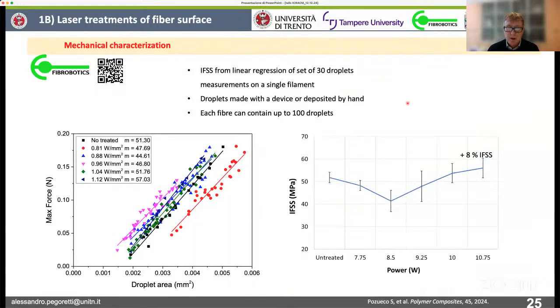The advantage of this technique is that a lot of points can be collected, so we can change the droplet area because by using the microscope on the machine, we can measure the size of the droplet, and the size is changing droplet by droplet. So we have a plot of the maximum force, which is the force I showed you before during the test, as a function of the droplet area. The slope of these lines represent the interfacial shear strength. So it can be converted into an interfacial shear strength, IFSS.